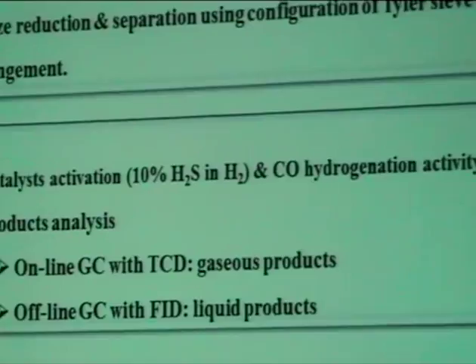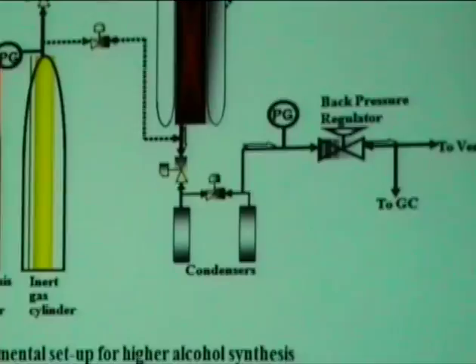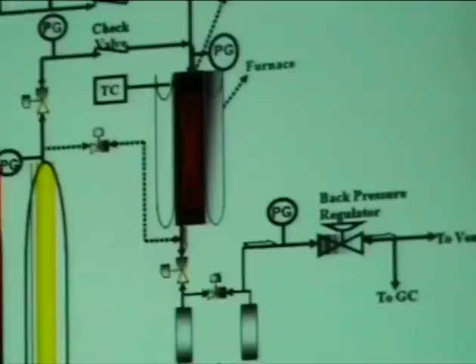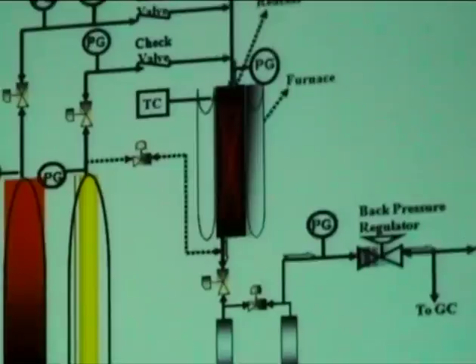For the reactor setup, fine catalyst particles were mixed with 90-mesh silicon carbide particles, and 46- and 16-mesh silicon carbide particles were placed on both sides of the main catalyst bed, along with 3-millimeter glass beads. This arrangement enhances solid-gas interaction so that plug flow is maintained and wall effects are minimized.